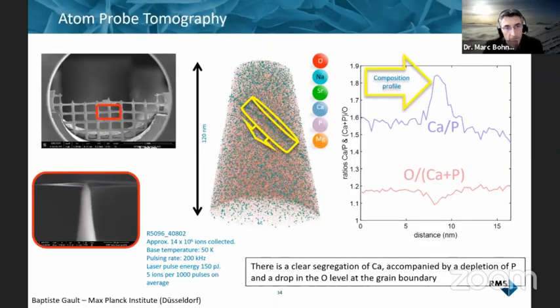We had the idea in the project to try to look at grain boundary composition by scanning TEM at EPFL, because that was the task that they were meant to do. And unfortunately, the scanning TEM did not have high enough resolution to detect changes at grain boundaries. So I talked to a friend of mine, Baptiste Gault, who is in Düsseldorf at the Max Planck Institute, and he gave it a try, or his postdoc Thorsten Schwarz, and we got really lucky the first time he tested the sample, because the sample didn't explode, which all the others basically did.